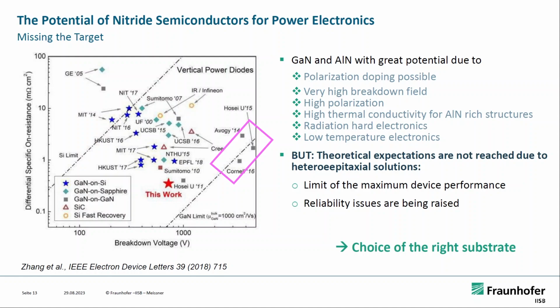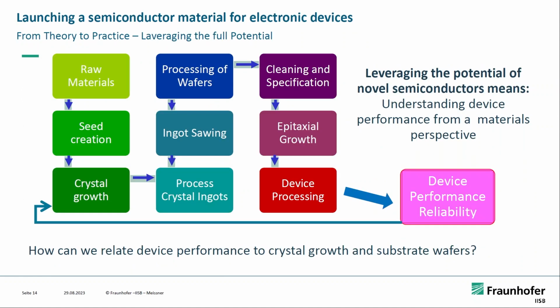There you see that the specific on-resistance versus breakdown voltage plot, which only monitors the physical expectation, gets closer to reality. This is not the case for any of the other solutions normally seen in nature. So the theoretical expectations, in my opinion, we don't reach because of limitations which come from the actual solutions. So the choice of the right substrate is key.